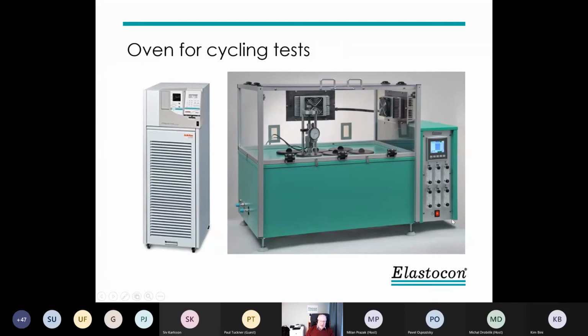To do this test, we have an aging oven with 6 cells, not with the same temperature. The temperature is controlled by a liquid thermostat to the left here, connected to the oven. Also here we keep the temperature constant up here, but we have a more forceful Peltier elements system there, so we can both heat and cool. We need to heat when we go up in temperature, and we need to cool when we go down in temperature.